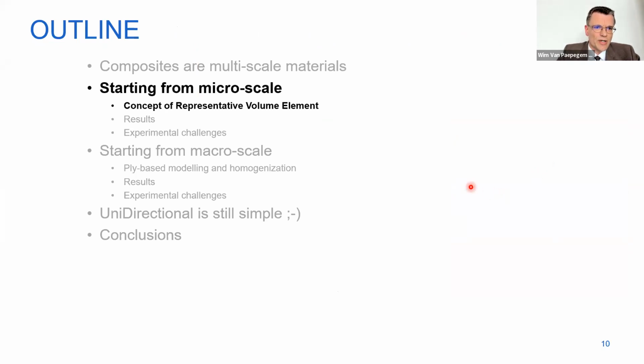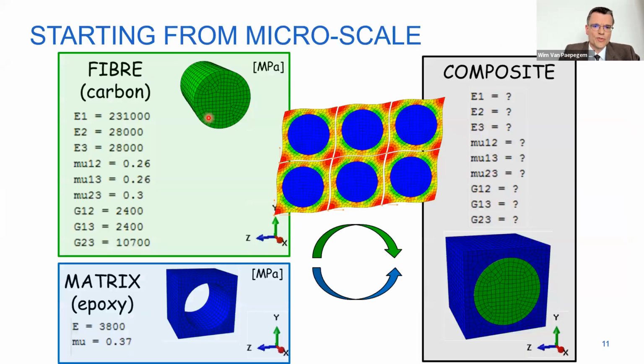So first starting from micro scale and introducing you a few concepts before we go to the results. First of all, if we start quite simple, what is our objective in micro scale modeling? We would like to start from the individual constituents, being the fiber and the polymer, and later also introduce the interface. In this case, we start just with elastic properties, to have the elastic properties of the fiber and the polymer. And here you can already notice that carbon fiber is not isotropic in stiffness, and the transverse stiffness is much lower.